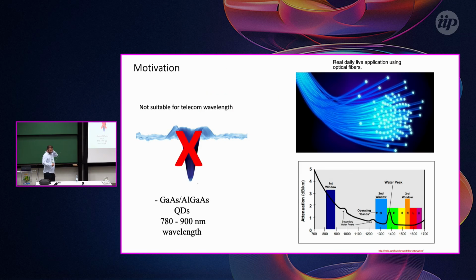The main issue of this quantum dot is that even with this approach that I just showed you, the emission wavelength is restricted to, let's say, 920 nanometers. But if you want to build a real quantum communication channel, it would be very nice if you could use the optical fiber infrastructure around the world. If you look at this graph of attenuation, with these local droplet etching quantum dots we are in the first window, where the attenuation is very, very high compared to the telecom frequency. What people are trying to develop in Europe now, at least in the groups that I know, is a source that has the good optical quality of the droplet etching quantum dots, but emits at telecom wavelength.